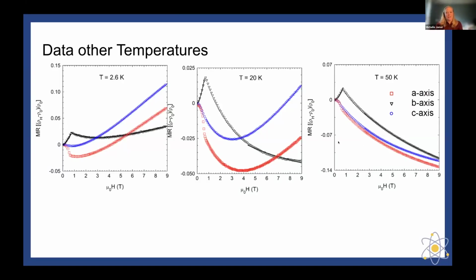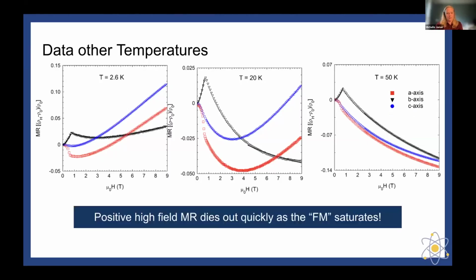50 Kelvin is going to be the temperature right before we hit the transition from ferromagnetism to the helical spin spiral state. And we start to see that we have a large negative magnetoresistance at higher fields, again indicative of a metal. But we do have this anomalous positive magnetoresistance along the B axis at all of these temperatures. So what we note here is that the positive high field magnetoresistance dies out quickly as the ferromagnet saturates, but this low field contribution still is sustained.